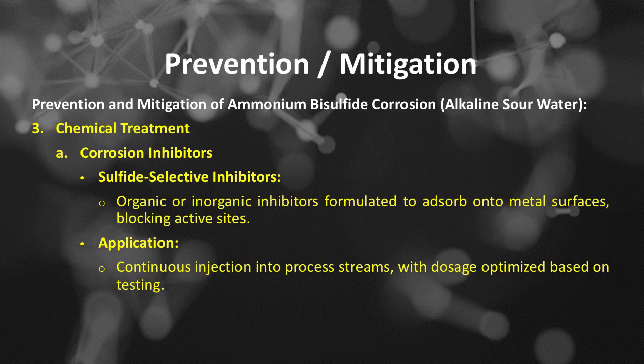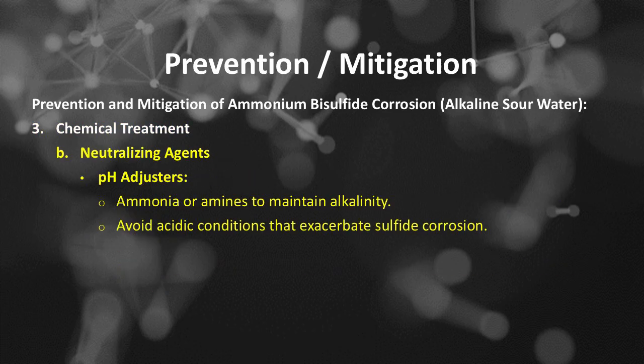Number 3 is chemical treatment. Number A, corrosion inhibitors. Sulfide-selective inhibitors, organic or inorganic inhibitors formulated to adsorb onto metal surfaces, blocking active sites. The application of corrosion inhibitors is by continuous injection into process streams, with dosage optimized based on testing. Chemical treatment. Number B is neutralizing agents, using pH adjusters, ammonia or amines to maintain alkalinity and avoid acidic conditions that exacerbate sulfide corrosion.